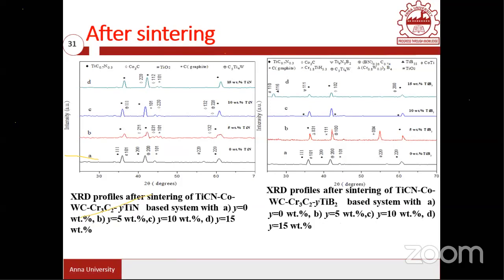After sintering, we have taken XRD, and it is giving some nice insights about the sintering. With the TiN, there is a formation of Co3C, from the carbon which sometimes comes out of the TiCN and reacts with the Co, forming some Co3C based phases. In a few places we have also seen gray carbon, graphite. And in the case of TiB2, it is really interesting.